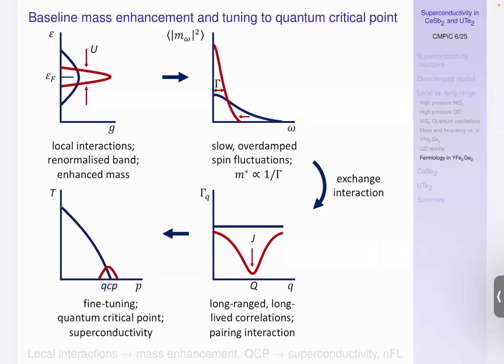So when they want to hop, it's hard, because they have to hop onto a place where the spins are also aligned in the same way already. So it basically impedes the motion of the electrons, slows them down, gives them a smaller Fermi velocity. Right? So we get narrow bands. On those narrow bands, you can then have likewise slow fluctuations, charge fluctuations and spin fluctuations. So you go from a broad fluctuation spectrum to a narrow fluctuation spectrum because you have narrow bands now.